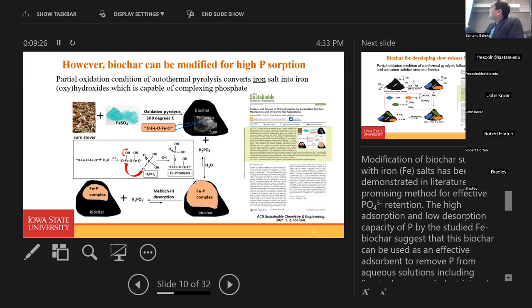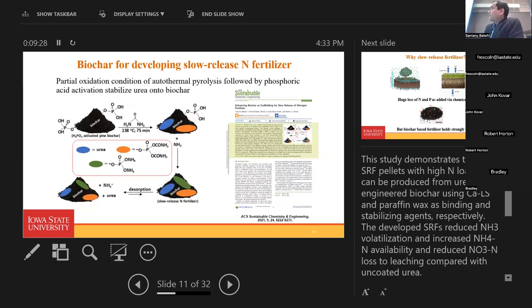So the biochar can be modified for high phosphate absorption. In the next slide, I'm showing that biochar can also be developed for slow-release nitrogen fertilizer. Partial oxidation condition of the autothermal pyrolysis followed by phosphoric acid activation can stabilize urea onto biochar.